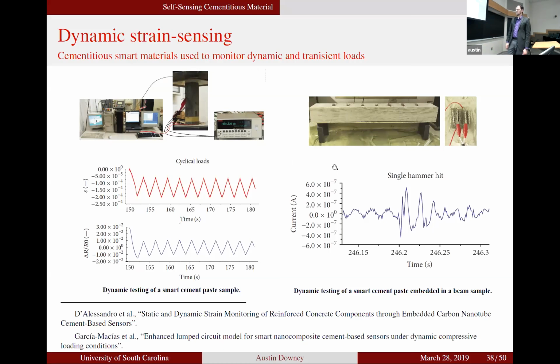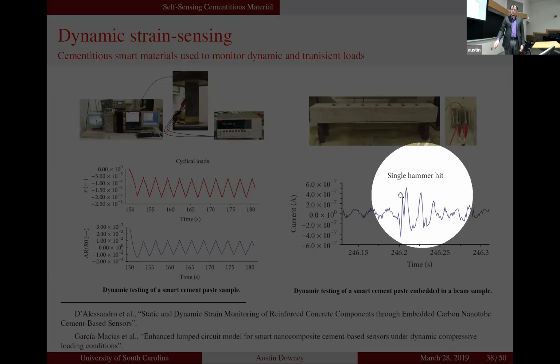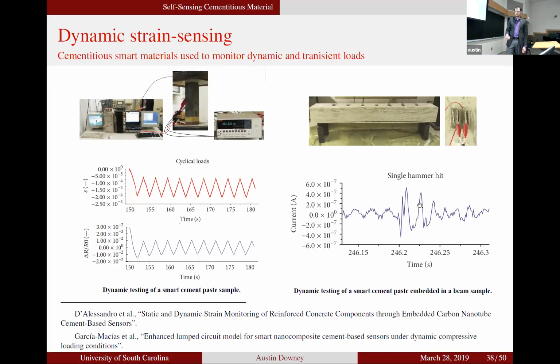So here we have a beam. We cast this beam in the summer of 2017. And then here, about 8 months later, we did a transient load once the concrete had dried. You impact it with the hammer, and you can detect the vibrations in the beam with the concrete sample itself embedded in.